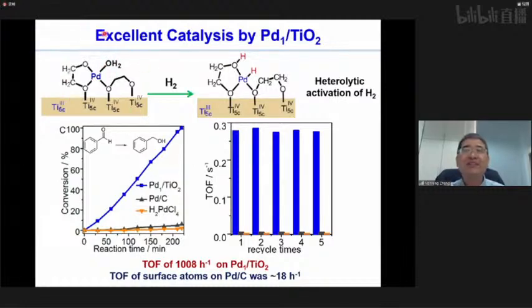With this coordination structure, once we introduce hydrogen, the hydrogen can get activated into hydride and proton. This is quite interesting because if we want to do the hydrogenation of a carbon-oxygen bond, we do need proton and hydride, right? Because the oxygen here has more negative charge and the carbon here has more positive charge. So we do need the help from both hydride and proton. That's why, if we use this catalyst for the hydrogenation of this ketone or this aldehyde, we can see a significant enhancement in their activity.